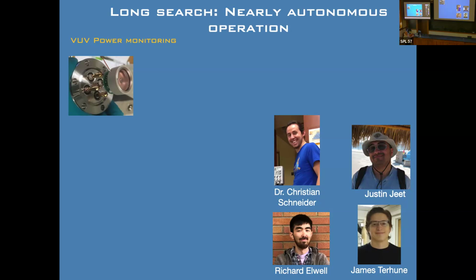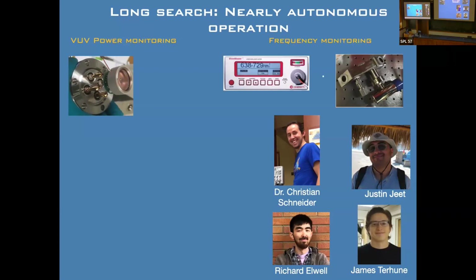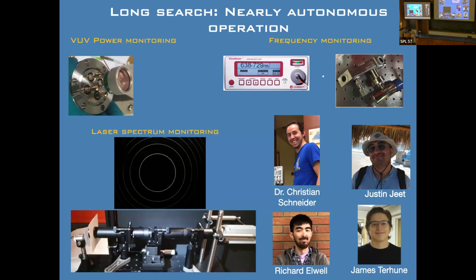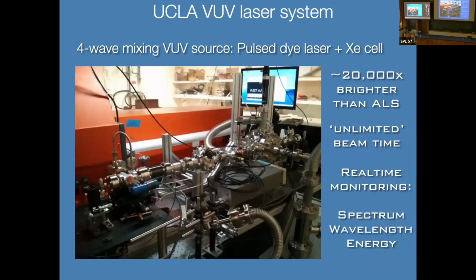Our first power meter measured negative power because the manufacturer had never actually used it and didn't think about the fact that you make photoelectrons when you hit things with VUV light. It was just all kinds of crazy stuff. We had to constantly monitor the mode spectrum of the laser, because you don't want to scan across the transition in the middle of the night right when the laser goes multi-mode and you never see it. You don't have the chance to really check this over and over as you would normally do. And so these guys spent a long time building this laser so it could run basically by itself.